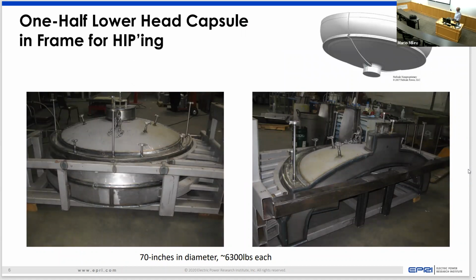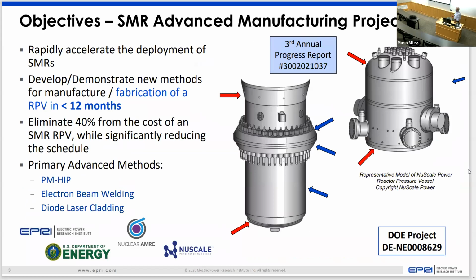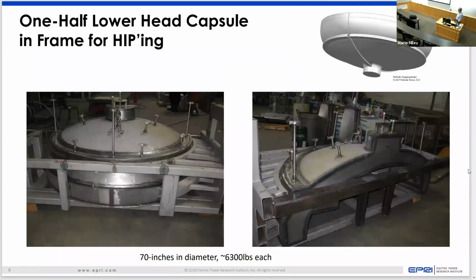We've also manufactured the lower section. So let me step back. This is the lower assembly, and this is the lower head that I'm getting ready to show you. You see the upper head on the first one on the right-hand side. So the lower section of this, we're actually making in 2 halves. Now, obviously, that's not the way we would do this normally. But again, we do not have a hot isostatic press large enough to do that. So we're making it in 2 sections and electron beam welding it together and then going through a heat treatment to actually get to the final properties that we're looking to get to.